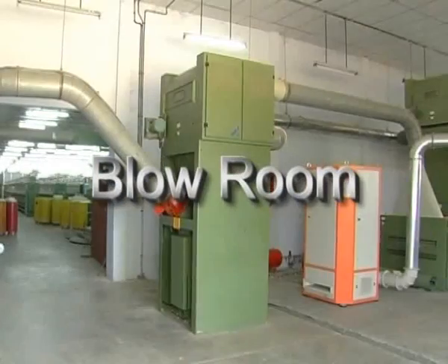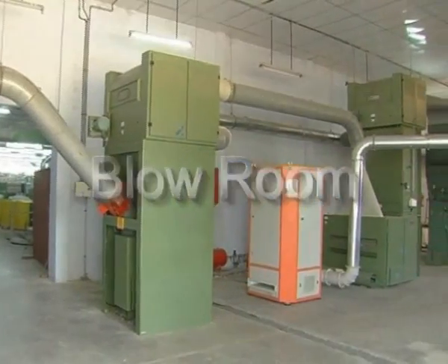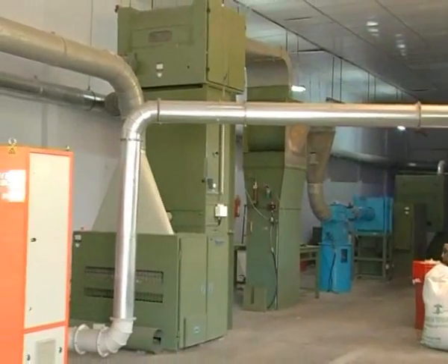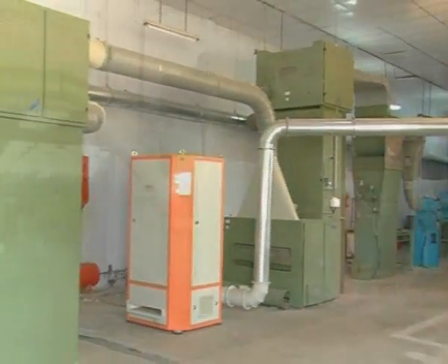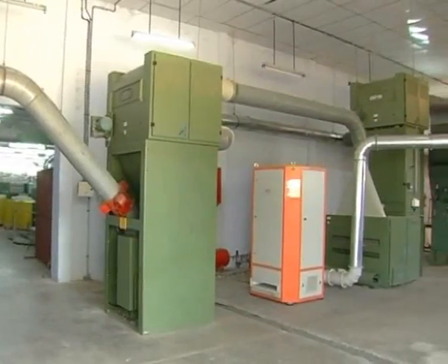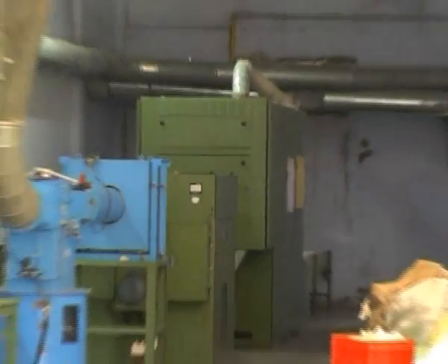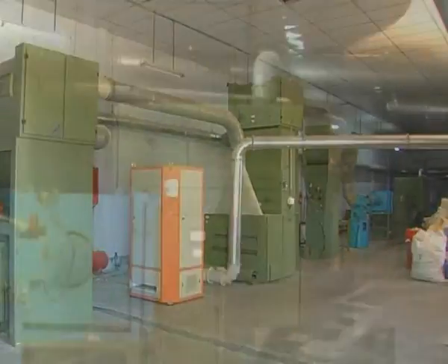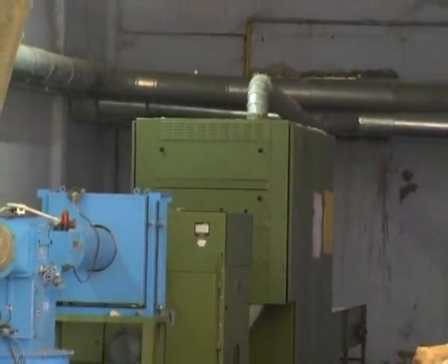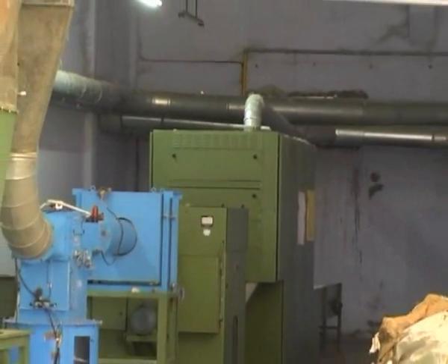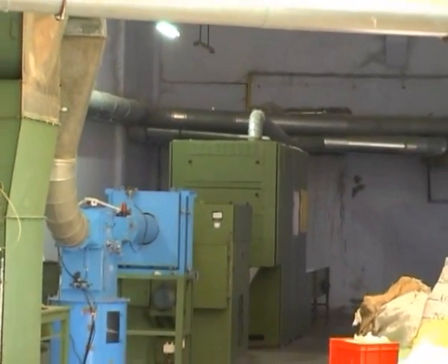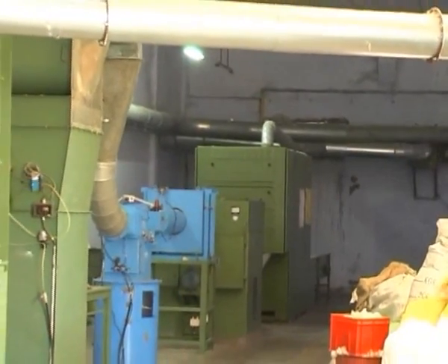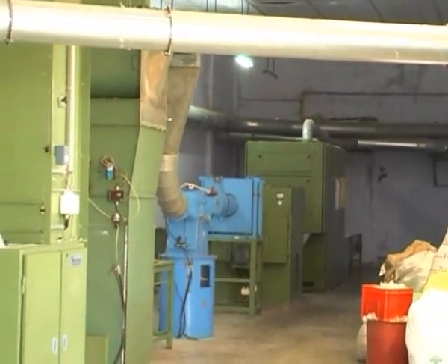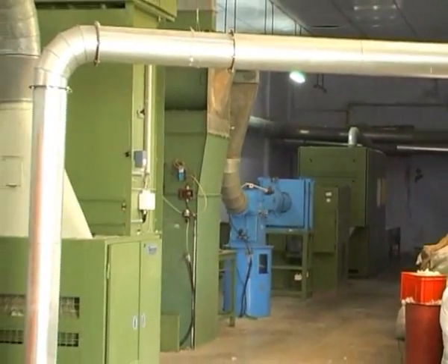Blow room. The material is passed through a blender which tumbles and breaks the bigger lumps into smaller tufts. This is then fed into a set of openers one after the other, which makes the tufts finer. The material is thus processed to separate trash, seed coats, foreign matter etc. from the cotton fibers. The processed material further passes through a finer opener and to the chute feed of the carding machines. In this process, entangled fibers are opened and most of the foreign matter is eliminated.